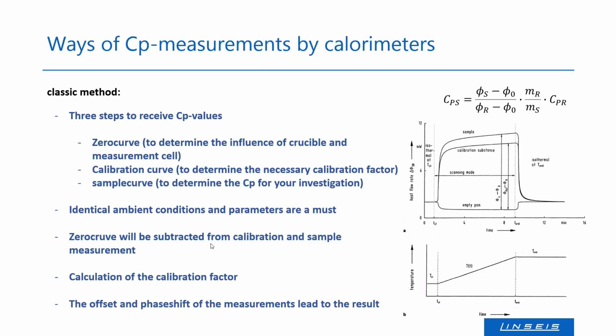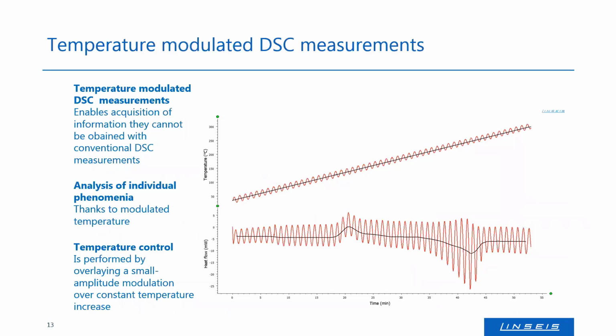Yeah, so that's it for the classic method, but let's talk about the temperature modulation way. So here we enable the acquisition of some additional information in comparison to the conventional DSC measurement. So we don't heat up anymore in a straight way, but we have a sine here on our measurement. So we have small amplitudes over our main temperature raise. And you can see here the conventional measurement in a black line at the upper part of this diagram. And the red one is the temperature modulated way.